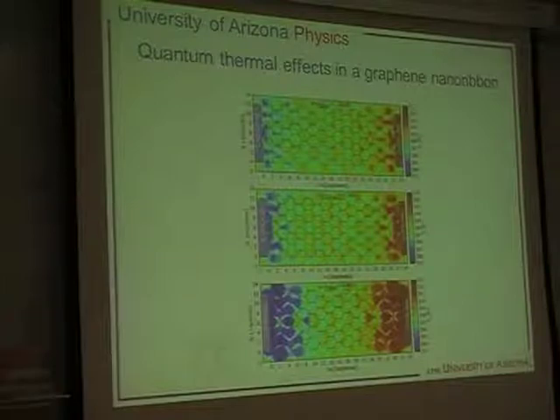And what I've shown here, like I showed you at the very beginning of the talk, is a graphene nanoribbon with the edges connected, basically covalently bonded, to hot and cold metal electrodes. What I've shown is the temperature distributions for 3 different gating situations of this graphene sheet. Here, the Dirac point is 1 eV above the Fermi level of the metal electrodes. Here it's half an eV above, and here it's a 20th of an eV above. And so you see the wavelength of these temperature oscillations gets longer and longer as you approach the Dirac point.